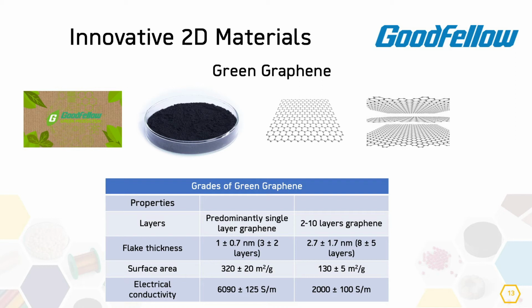and actually we can use this hazardous gas, and we are processing and decomposing it into hydrogen and elemental carbon in a plasma reactor. Actually, this reactor is vibrating, and it's very interesting. Another interesting factor is that the elapsed time from methane gas entering the plasma reactor to the point when graphene is formed is less than 1 second. That means that the production of graphene can be massive. I mean, it's amazing. At that point, few layer graphene is formed, and we can have the 2 to 10 layers graphene, as you can see on the table.